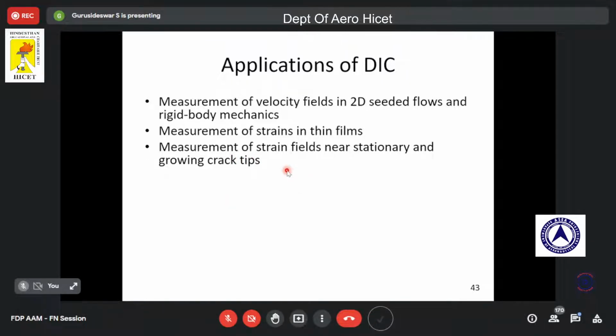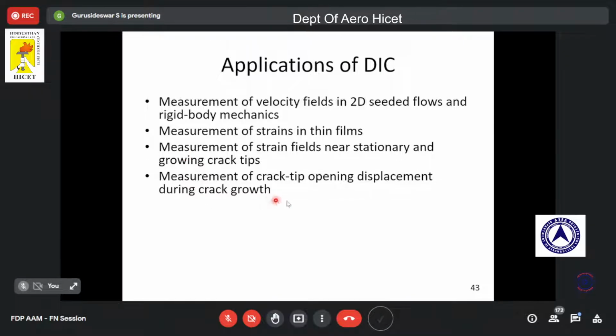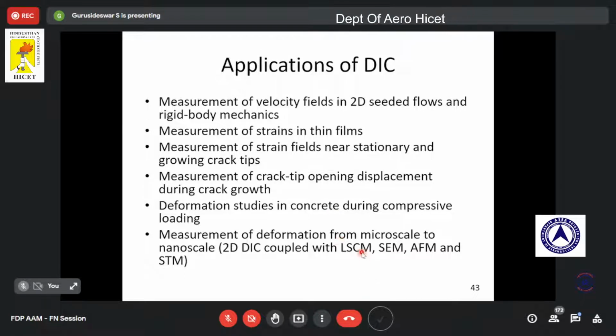In fracture mechanics, we know that at the crack tip we experience a large strain. So to understand the strain field at the crack tip, we can go for DIC, and we can also use DIC for crack tip opening displacement. We also use DIC in concrete to get strain data. So it has a wide range of applications, and it is a non-contact measurement technique. So this is the application of DIC.